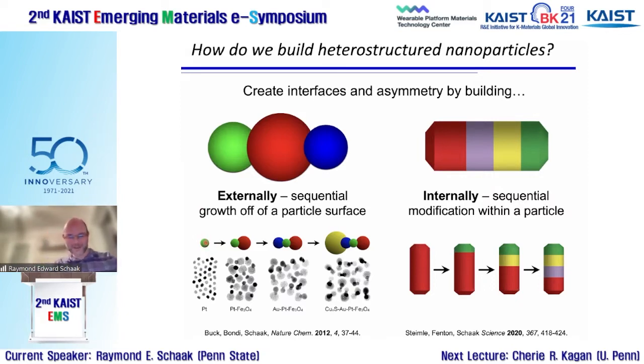This is something we did almost a decade ago. Time flies, right? We took platinum nanoparticles and grew iron oxide off of them. This is known chemistry, around before we got into the field as well. These are well-known reactions for growing another nanoparticle off of a nanoparticle. Getting back to some of the panel questions about relating nanoparticle and material synthesis to organic molecules, this looks more like a total synthesis, like a multi-step reaction that increases functionality and functional group diversity at each step. And so we do a lot of seeded growth reactions where we sequentially grow particles off of another particle's surface.